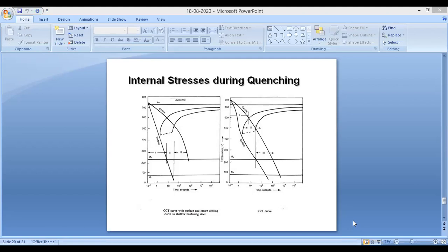The development of internal stresses during hardening cannot be fully avoided, but can be reduced by using different methods of cooling, such as tempering, etc. In industrial practice, wherever practicable, surface hardening is performed rather than through hardening for tools and machine parts if it can give good life in application. This is because the usually compressive nature of internal stresses obtained in these methods makes the surface layers bear a greater amount of tensile stress. That is, the strength of the surface is increased. This advantage, which increases the life of the part, is used, for example, in leaf springs by shot peening the surfaces to induce compressive stresses before putting them in actual service.